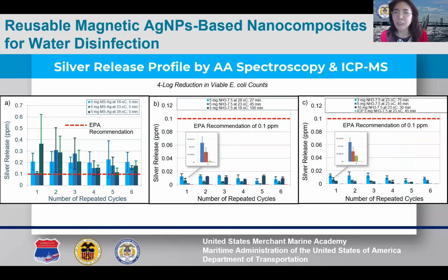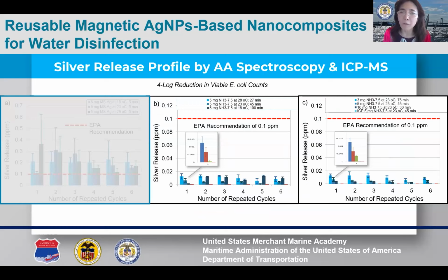We investigated the leaching of silver ions into water from MS-Ag and NH3-7.5 during 6 repeated shaking cycles, each corresponding to a 4-log reduction in viable E. coli counts. The silver content in each supernatant was determined by AA spectroscopy with a detection limit of 1.5 parts per billion. Figures B and C reveal that for all NH3-7.5 samples across the 6 cycles, the silver release